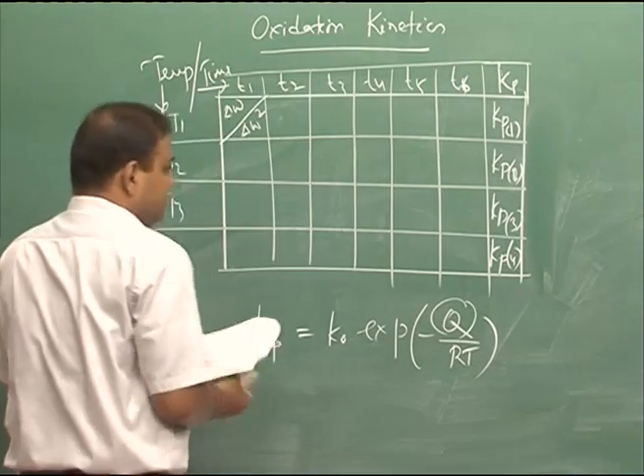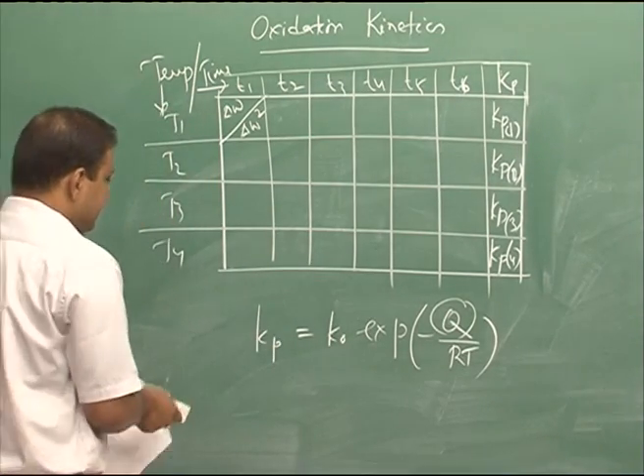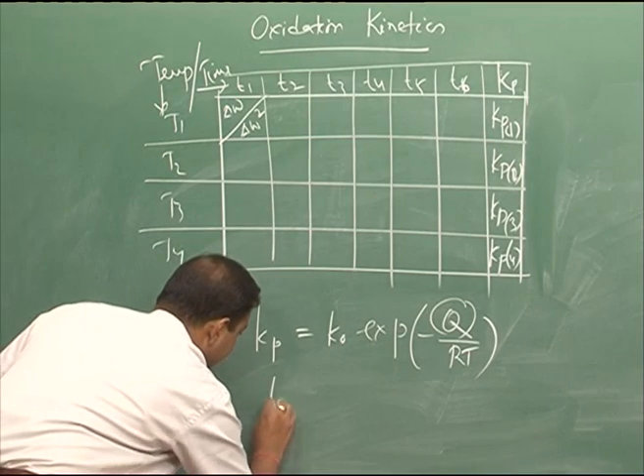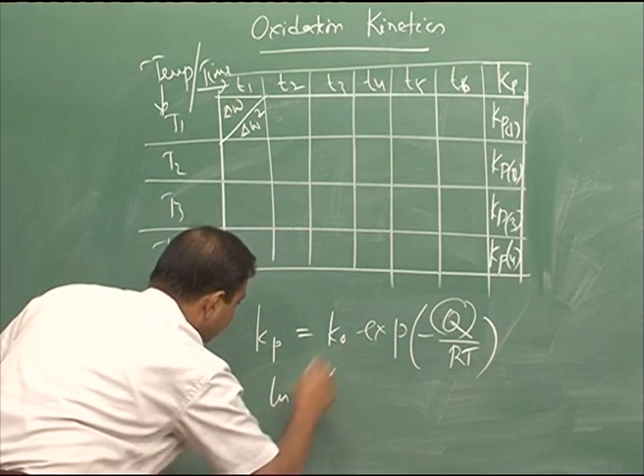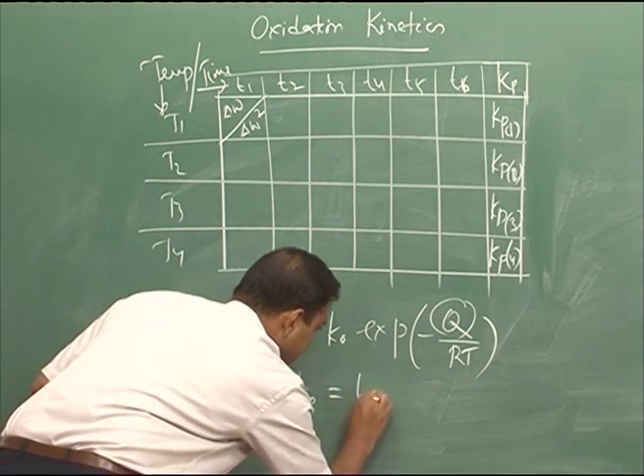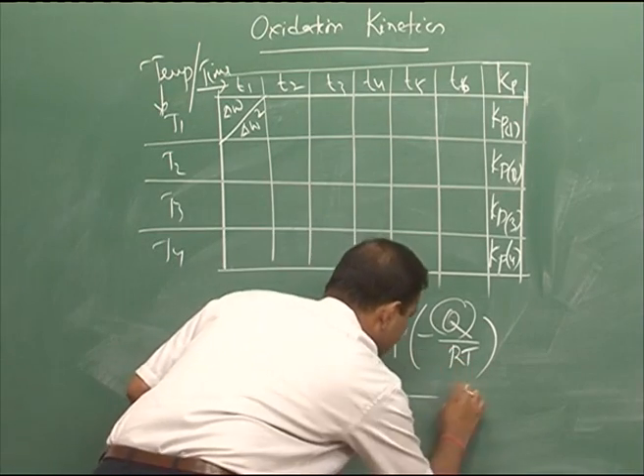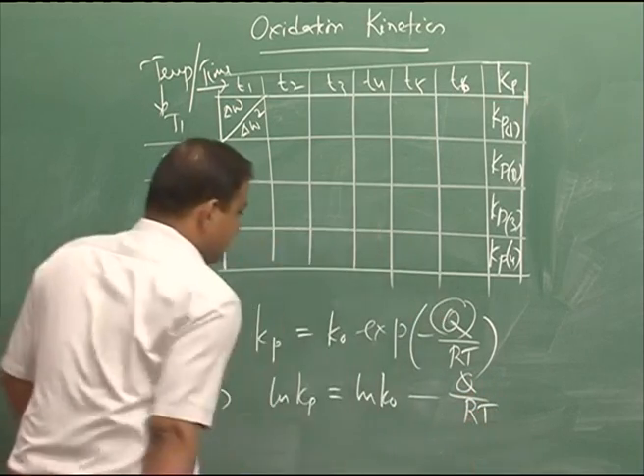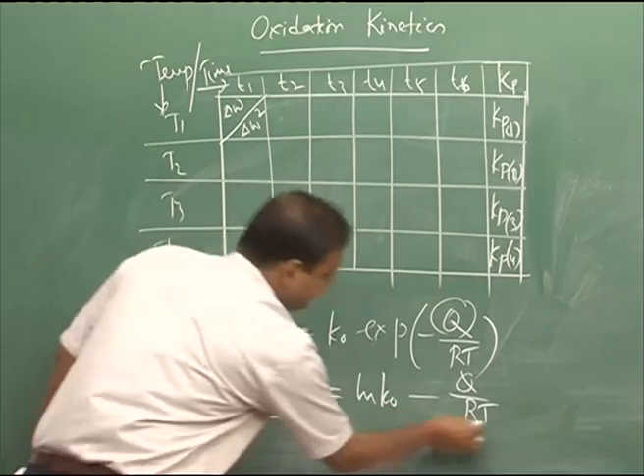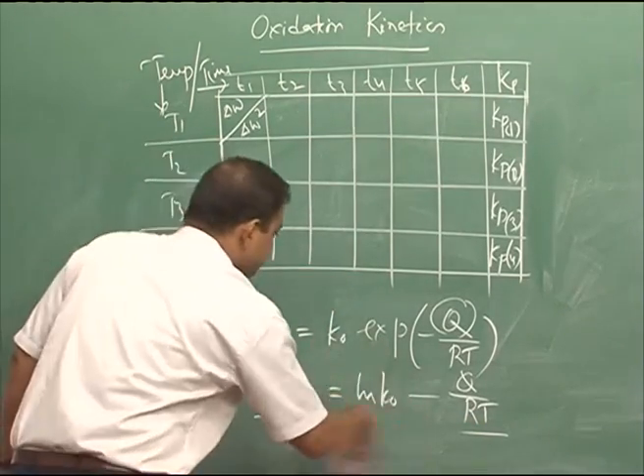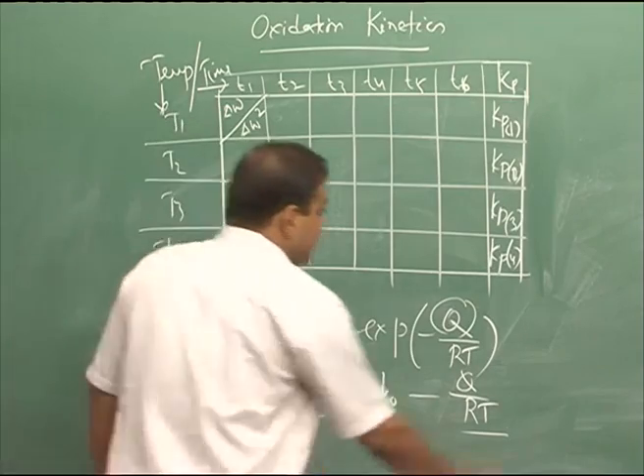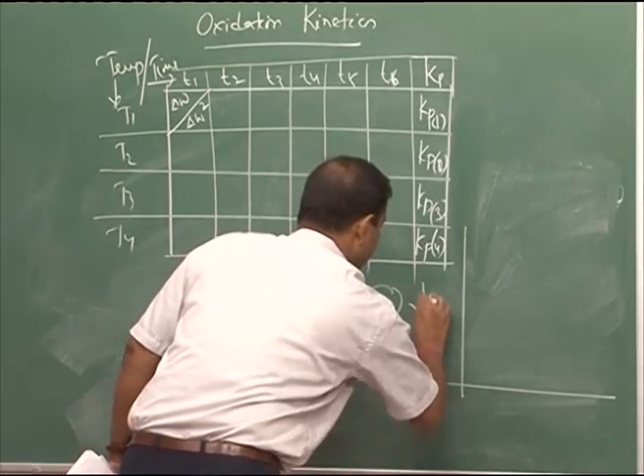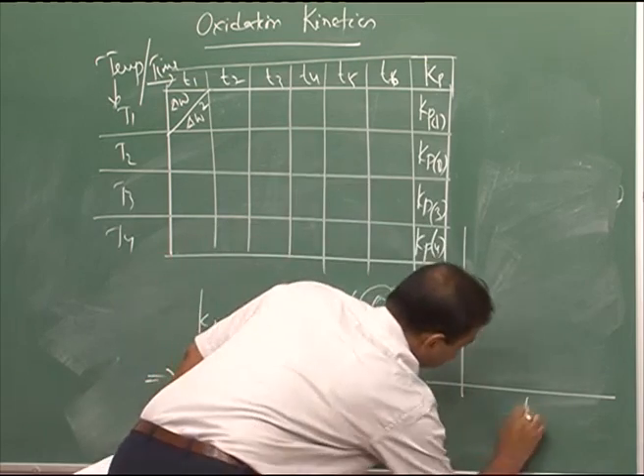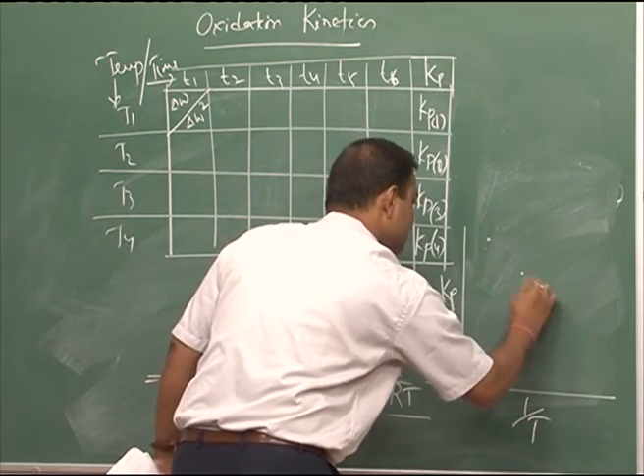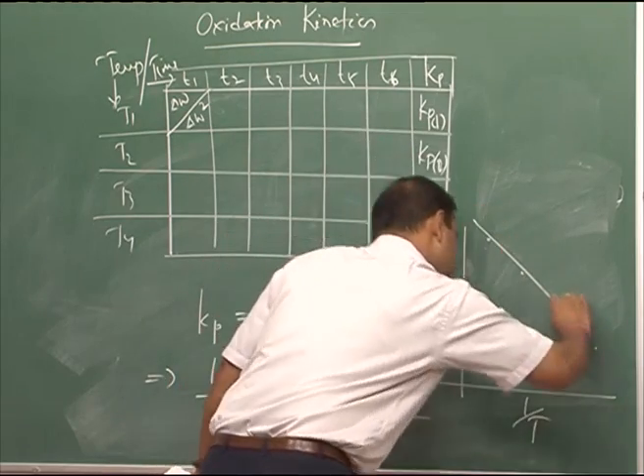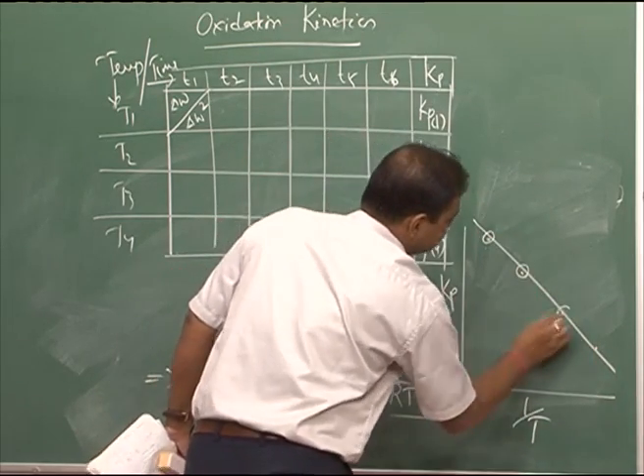Now, if we take the logarithm of both ends, ln K P would be equal to ln K 0 minus Q by R T. Now, if we plot ln K P as a function of 1 by T, we will see that this relation gives a linear plot. Let us connect it. So, these are all the points.